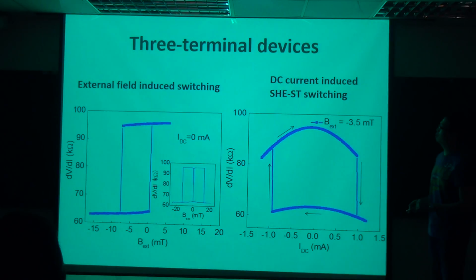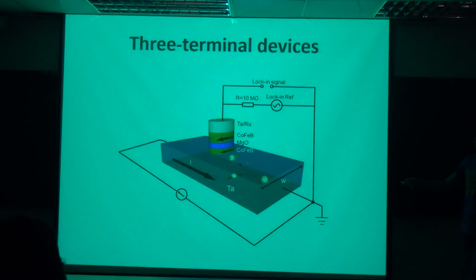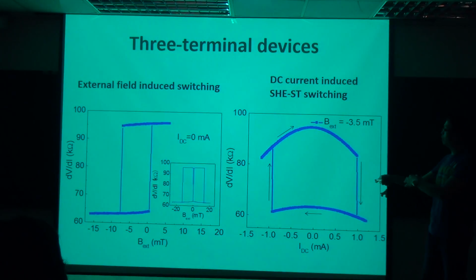So these are the data from the device, using external field induced switching, so by applying an external magnetic field, we just want to check the quality of the device. And yes, we have TMR of about 50%. And more importantly, if we apply current, so this is the current flowing in the tantalum layer to generate spin Hall effect, we can switch the device from a low resistance state, which means that these two layers are parallel to each other, to a high resistance state, which means that the bottom layer has been switched by the current-induced spin Hall effect. And you can see the data is very clean and also very symmetric. And that's also what you should expect from spin Hall effect switching.